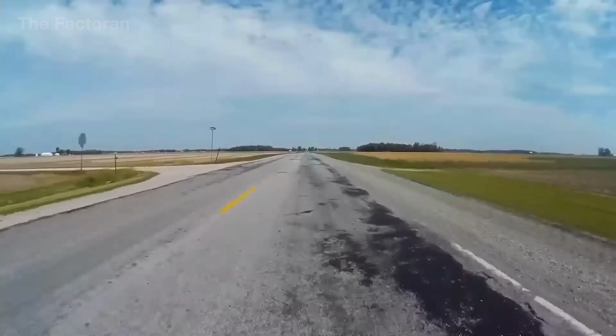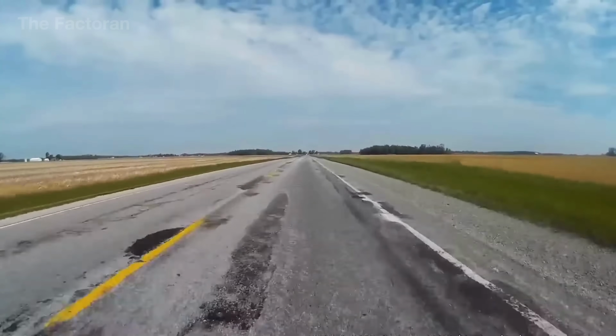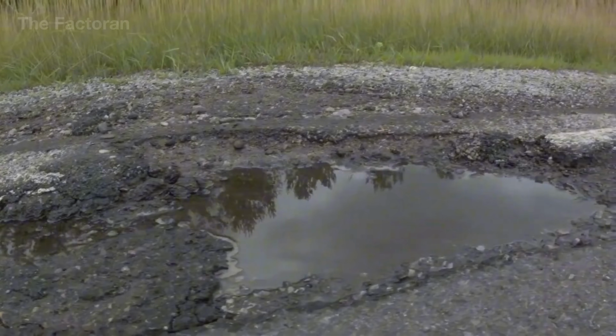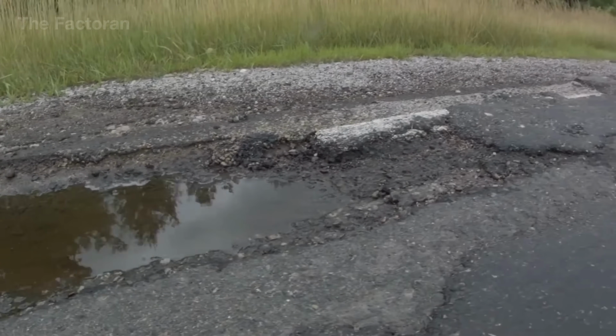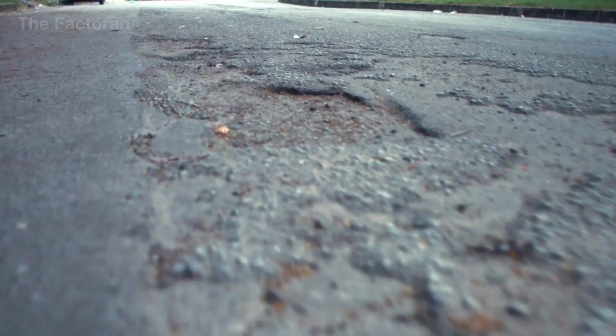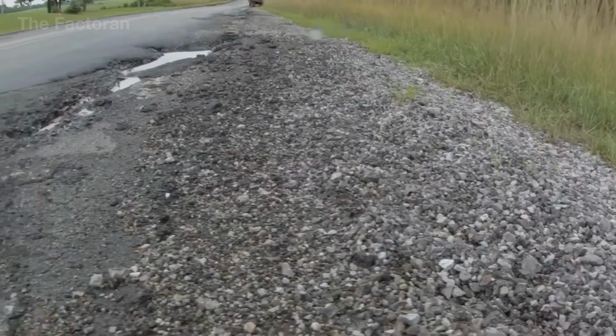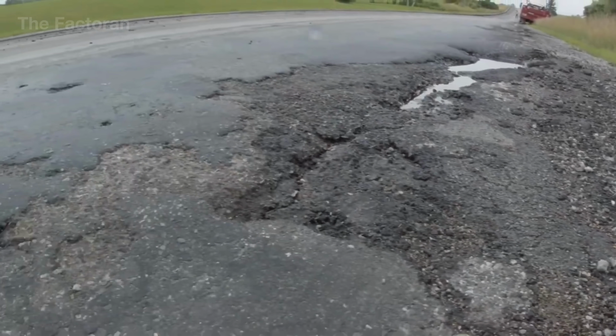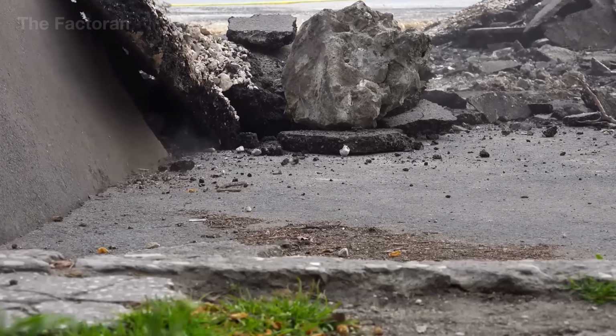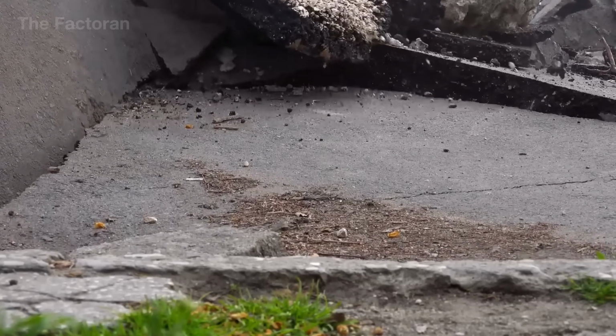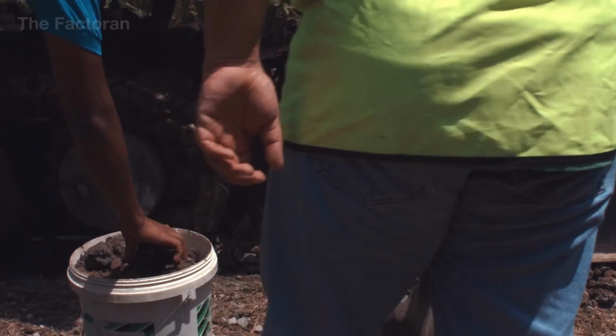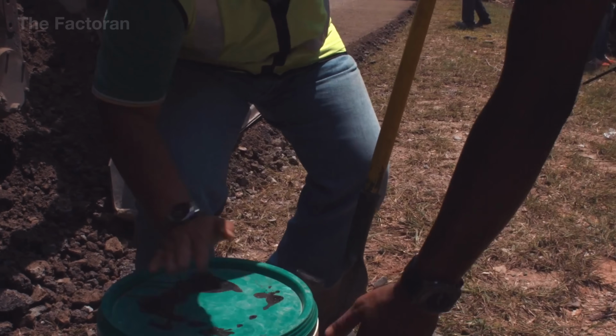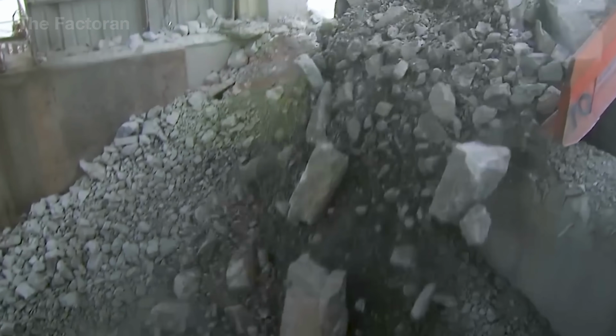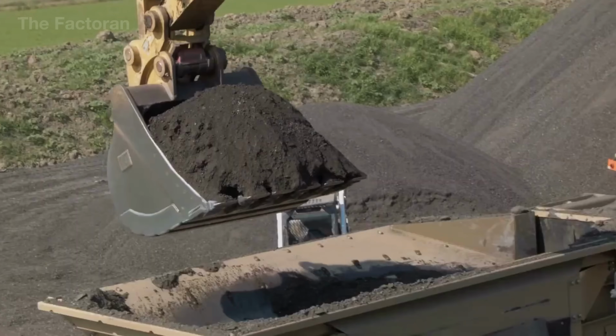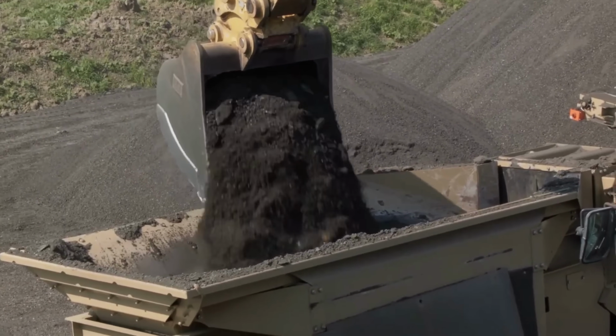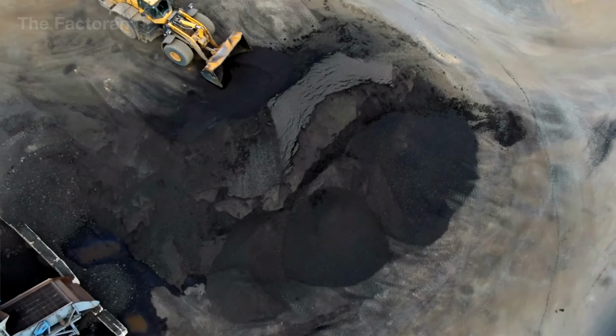In the life cycle of a road, when the surface layer becomes worn, it is not discarded, but reclaimed for recycling. Specialized milling machines cut away several inches of old asphalt, grinding it into small particles on site. This material, known as RAP, reclaimed asphalt pavement, contains both used aggregates and aged binders still clinging to the stone. Tons of RAP are transported back to the plant, unloaded into dedicated storage bins for reuse. At the plant, RAP undergoes a closed-loop process.